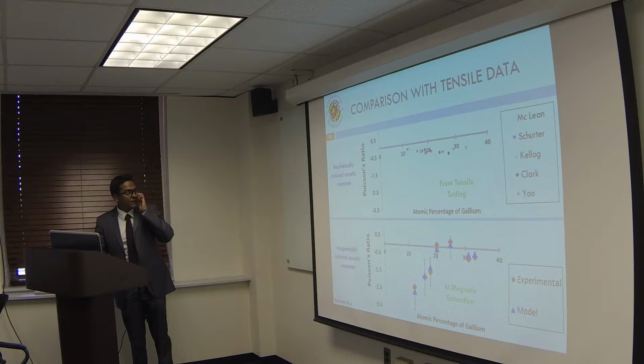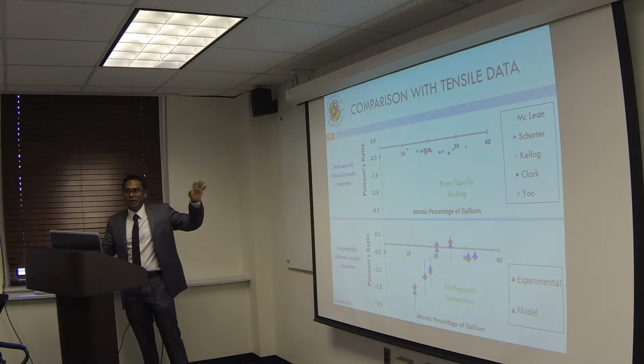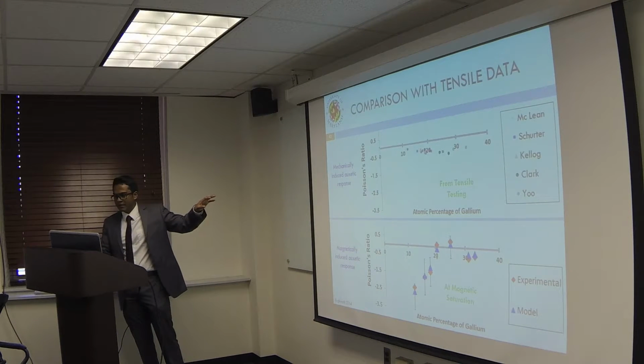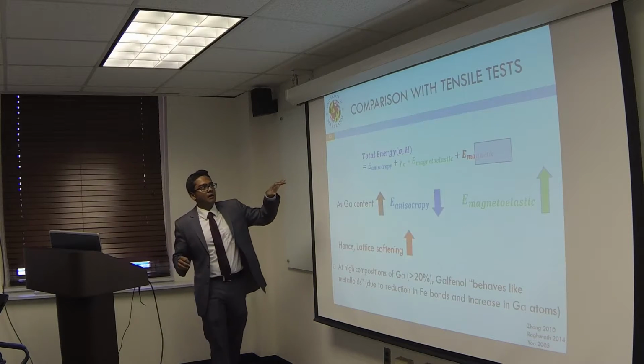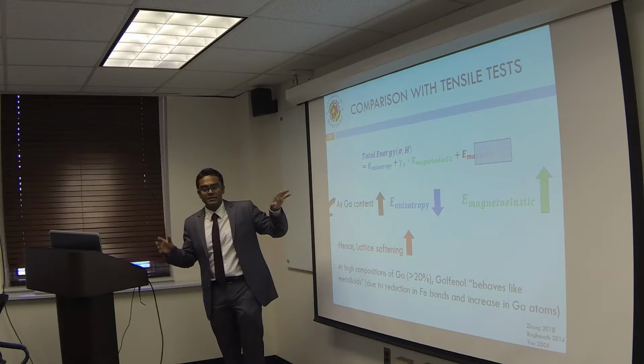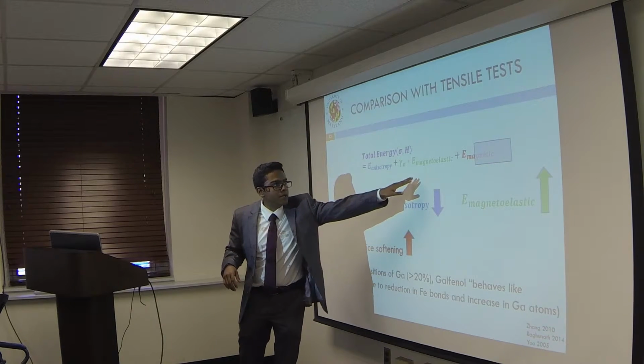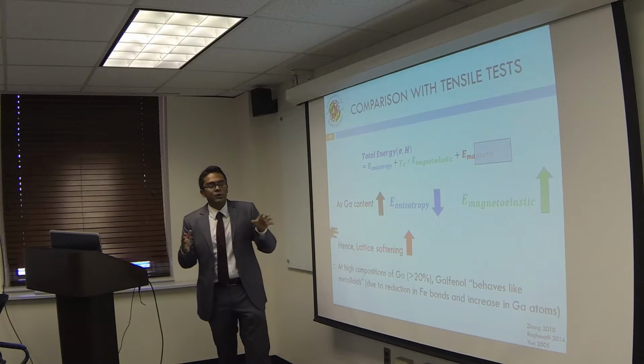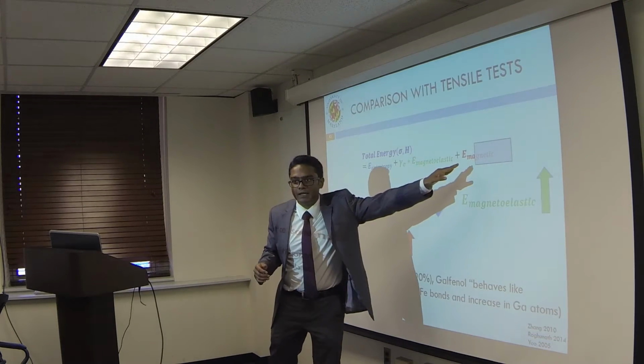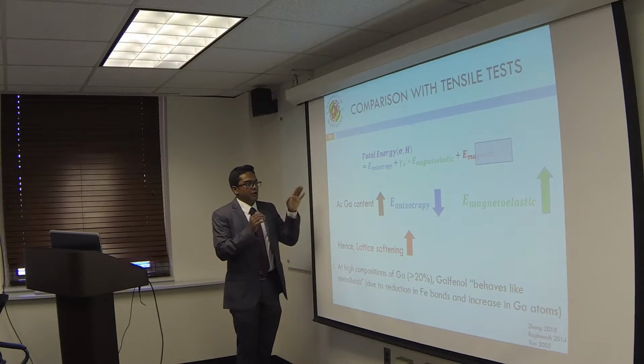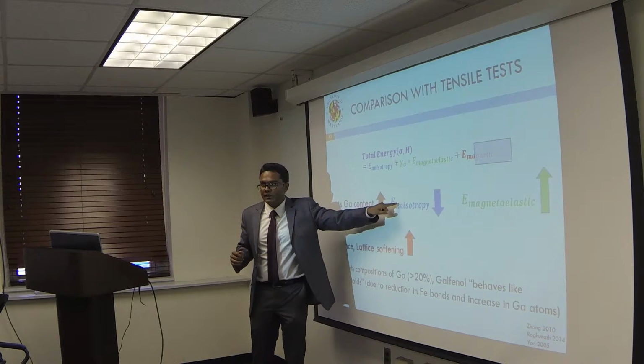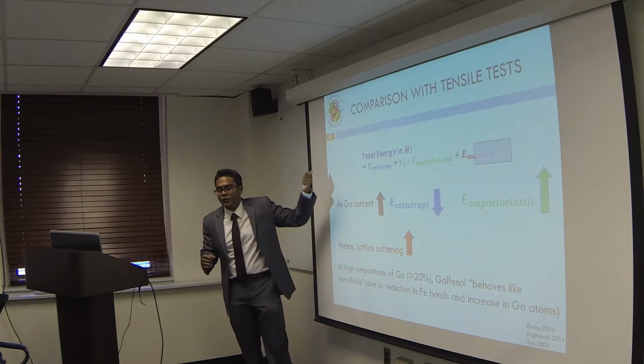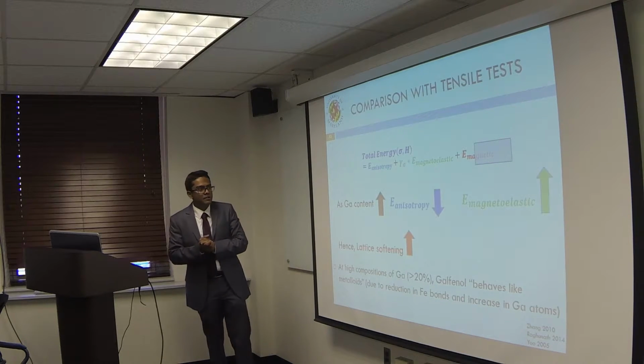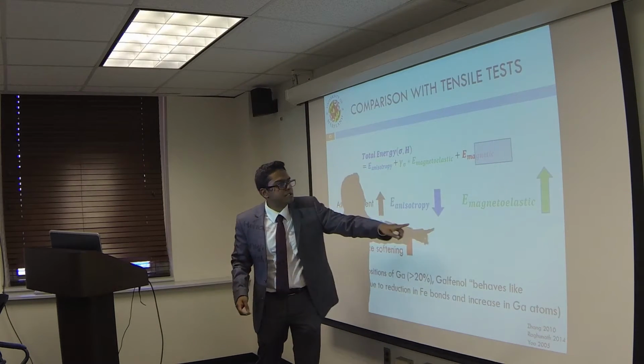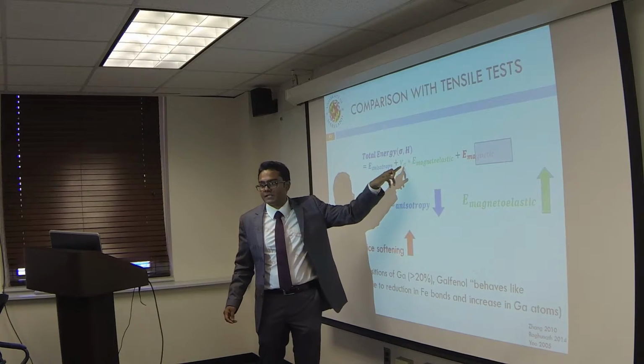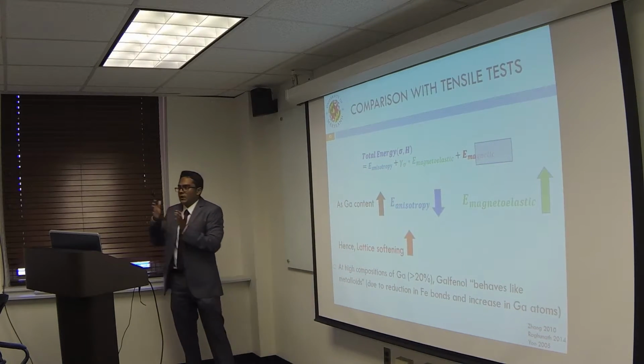All right. So going back, we see an opposite trend between applied mechanical loads and magnetic fields. To understand this, let's look at the energies that are involved in the magnetoelastic system. We have the anisotropy energy, the magnetoelastic energy, and the magnetic energies. When it comes to applied tensile loads, we don't really apply any magnetic energy, so we're going to take that term out. As the gallium content increases, we know that the anisotropy decreases from the curves that I showed when I was discussing the drawbacks of the simulations. And when anisotropy decreases, the magnetoelastic energy increases because of the applied stresses. And this leads to lattice softening.